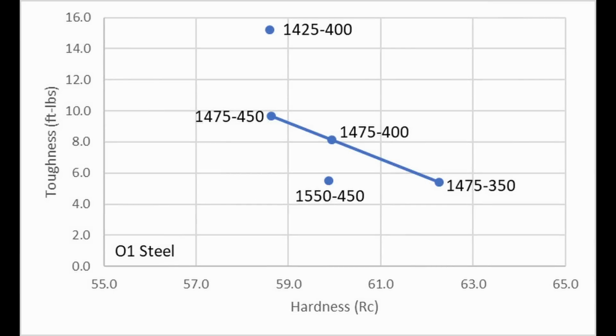But moving on to O1. O1 is definitely a steel that can have issues with plate martensite. And I have shown that with some prior experiments that I did with O1, where I austenitized at 1550, 1475, and 1425. The reason for the different austenitizing temperatures is if we austenitize lower, we dissolve less carbide and get less carbon in solution, therefore less plate martensite. And indeed, when we compare the toughness, even at the same level of hardness, when I austenitized lower, the toughness was higher. So we want to avoid plate martensite in O1.